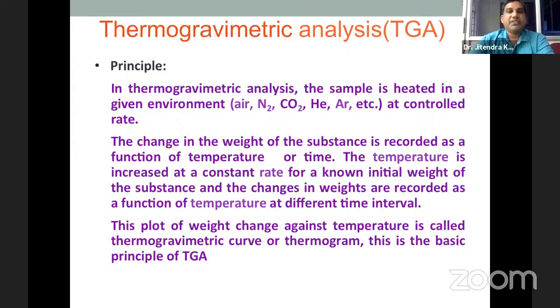So next we move to thermogravimetric analysis. In this we check the thermal stability of any compound, even if we develop some new coatings. What is the thermal stability of those coatings? That is very important in any paper, and they can widely ask. If you want to use those coatings in a turbine, and the turbine is running at approximately 1000 degrees centigrade, then this TGA plays a very important role. If your coating is not sustained up to more than 1000 degrees centigrade, then those coatings are useless.